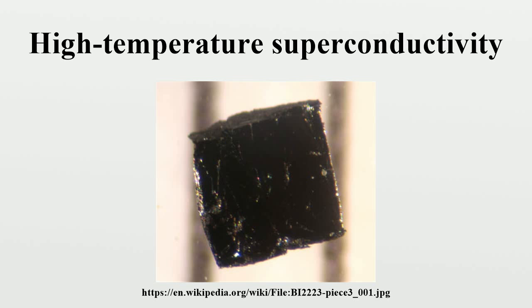The confirmation of the d-wave nature of the cuprate superconductors was made by a variety of experiments, including the direct observation of the d-wave nodes in the excitation spectrum through angle-resolved photoemission spectroscopy, the observation of a half-integer flux in tunneling experiments, and indirectly from the temperature dependence of the penetration depth, specific heat and thermal conductivity. The superconductor with the highest transition temperature that has been confirmed by multiple independent research groups is mercury barium calcium copper oxide at around 133 K. After more than 20 years of intensive research, the origin of high-temperature superconductivity is still not clear, but it seems that instead of electron-phonon attraction mechanisms, as in conventional superconductivity, one is dealing with genuine electronic mechanisms, and instead of s-wave pairing, d-waves are substantial. One goal of all this research is room temperature superconductivity.